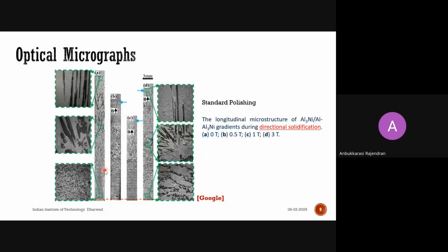You can prepare the sample in this direction vertically, or if you want to measure the strength of an individual region, you can prepare your sample horizontally. If my interest is to measure the strength of this particular phase, I can prepare the sample horizontally. If I want to measure the strength across the interface, I can prepare the sample vertically. Ensure that your interface falls at the middle of the standard sample. Then you do the test, so you can come to know the strength of your interface. If it is too thin, you can go for a bend test also.